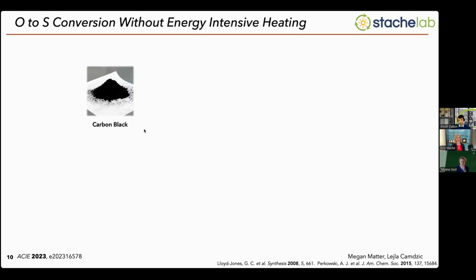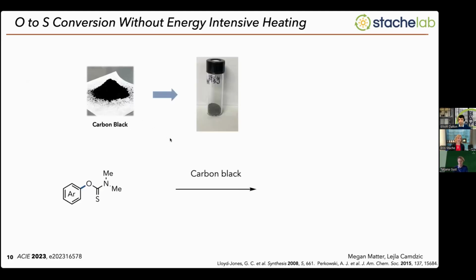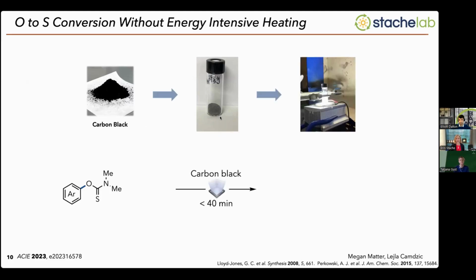So carbon black, as Tatiana mentioned, is ubiquitous. You can find it everywhere. Most of the black materials out there are using some sort of carbon black pigment. And so what Megan did is she took carbon black, she mixed it with the substrate. So this is just solid mixing the two powders together, and then takes this vial and irradiates it with visible light, so just broad spectrum white light, for up to 40 minutes. Some of these reactions are done in less than 5 minutes, actually.